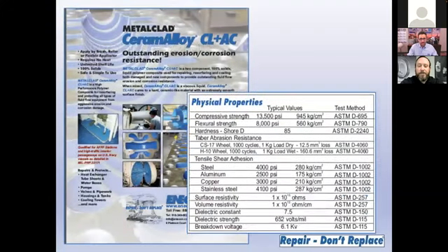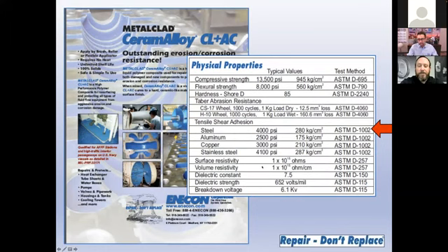CeramAlloy's 4,000 PSI tensile shear adhesion to prepared steel surfaces helps give our customers the confidence that we can provide them long-term solutions. Since rust can exert a force of 2,000 psi on untreated metal surfaces, our 4,000 psi adhesion in these areas basically eliminates any chance of underfilm corrosion and catastrophic system failure if the ceramic alloy is ever damaged during operation. This allows for very easy in-field touch-ups when routine maintenance is undertaken during plant shutdowns.